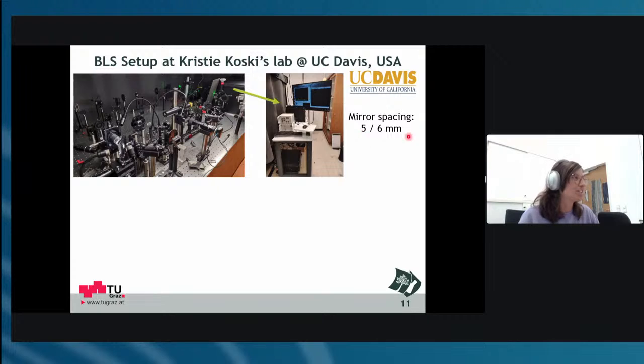I mentioned that the distance between the mirrors is pretty important because it determines the frequency range that you are measuring. And I was at around 5 to 6 millimeters of mirror spacing. That's always between 20 and 30 gigahertz on each side.